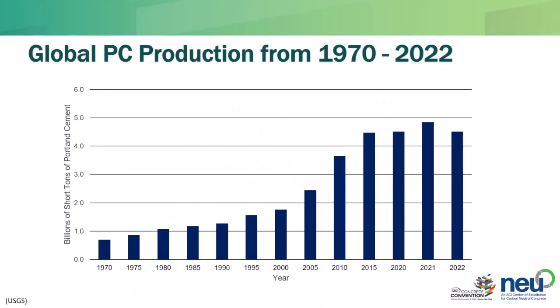But when you consider that we're producing lots and lots and lots of concrete annually, then the carbon issue becomes big, right? And this is global Portland cement production from the 70s through more recently. You can see it's increasing, bouncing around a little bit, but it's really high, right? Over 4 billion short tons of Portland cement, and this is just cement, making up 12% of concrete maybe. So that's a lot of concrete that we're continuing to produce. So the carbon footprint, you hear between 5 and 8% of global anthropogenic CO2, and that's an issue.